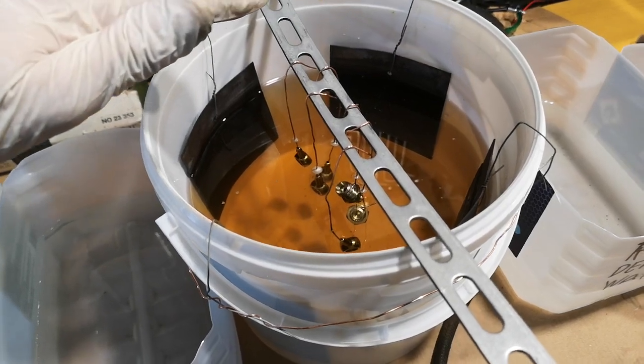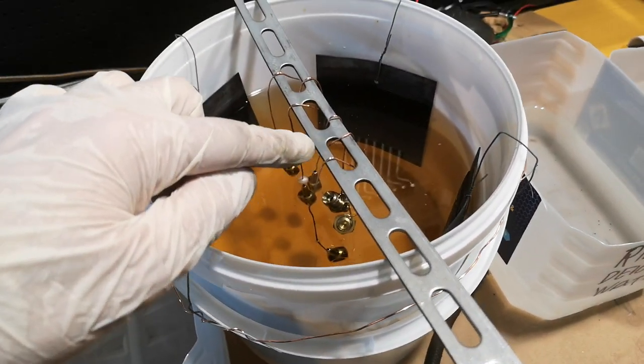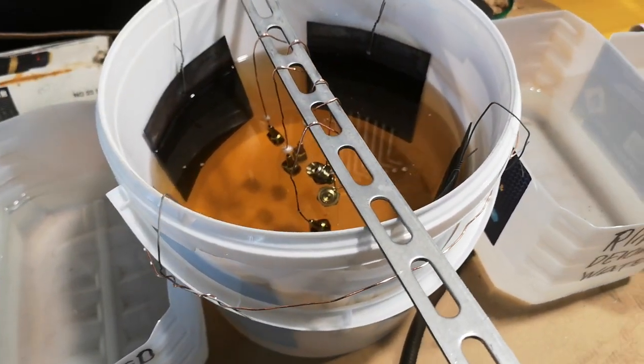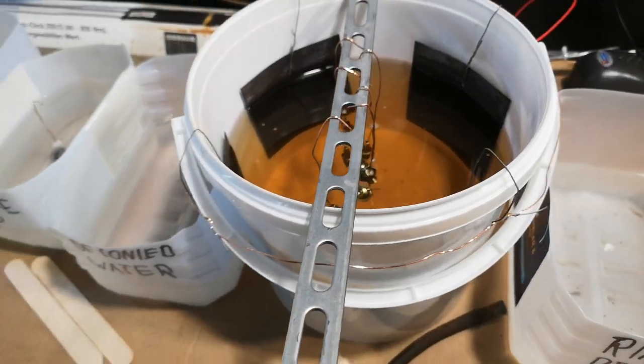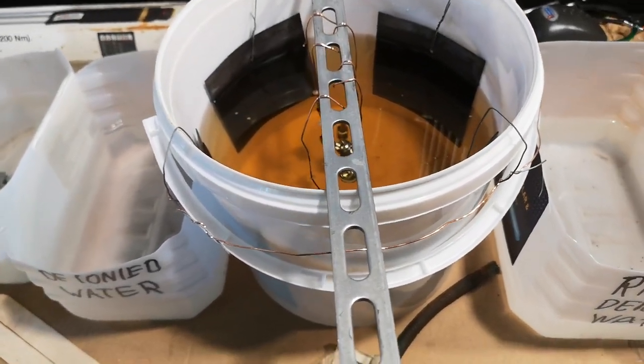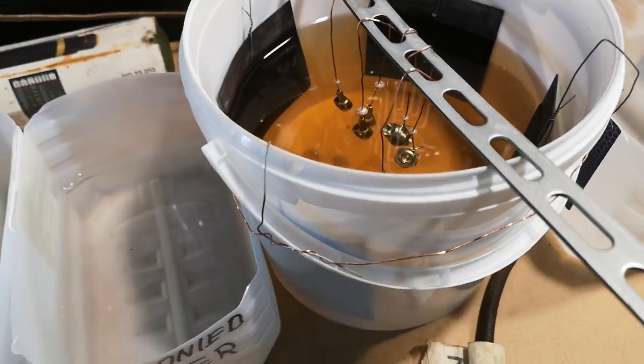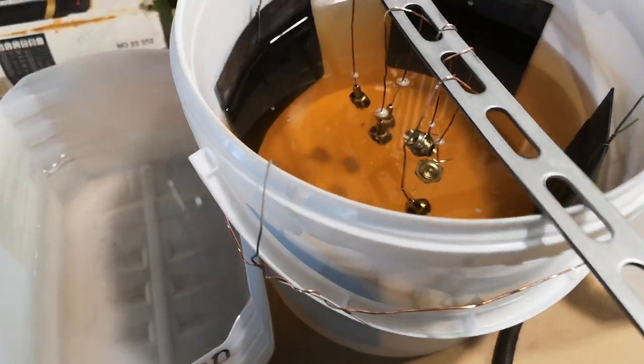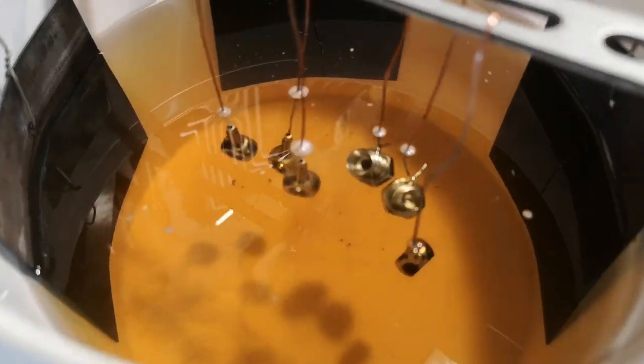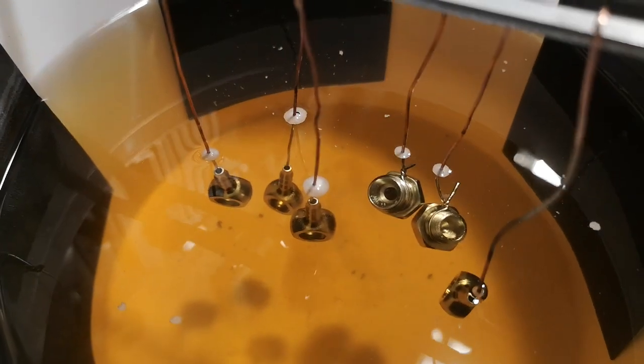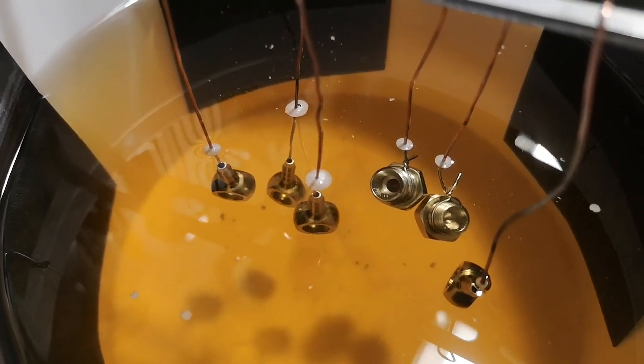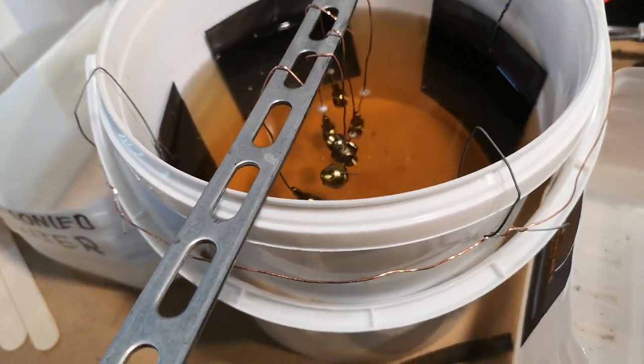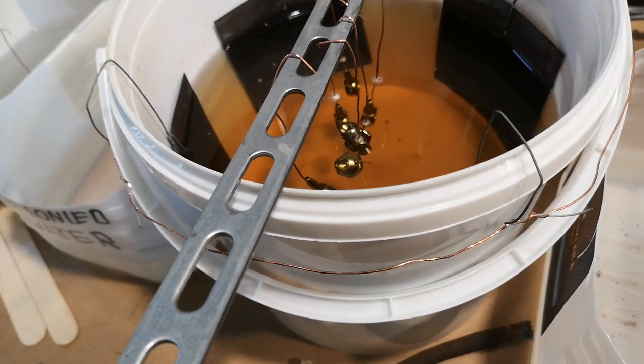I clean the surface every day with Scotch-Brite. I clean the surface of the wires each time before I'm putting it here, also with Scotch-Brite to ensure that I have good electrical connections. These parts are actually bathing or electroplating for quite some time. And there also is a reaction that frees some bubbles, as you can see on the surface here. At the beginning there's more bubbles. After a while the bubbles stop, which tells you that the whole part is covered.